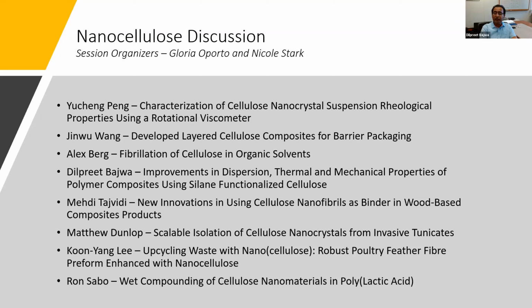So going forward, we are now looking at using these silane treated cellulose nanocrystals in the high density polyethylene matrix to see if we are able to replicate the results that we saw in the PEO polymer. Although PEO was a hydrophilic polymer, now HDPE is going to be hydrophobic. So we are going to see in the next couple of months how this functionalization helps us in hydrophobic polymer matrices. So that is the nutshell of our research findings: overall, the 1 to 1 CNC and silane helped us to improve the properties and dispersion in the PEO matrix. And I'll be open to any questions.